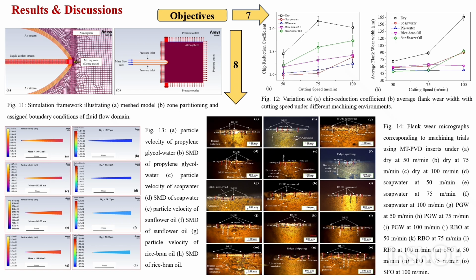Here in the MQL study, we can see the SMD, Sauter mean diameter, for soap water and propylene glycol were low, as well as the particle velocity were high. Here we can see from the graphs, both soap water and propylene glycol had led to favorable results, but at higher speed soap water had suffered surfactant degradation and micelle formation, but due to glycol's enhanced thermal stability, propylene glycol didn't. So that's why better responses were obtained between the two with propylene glycol water as a cutting fluid.